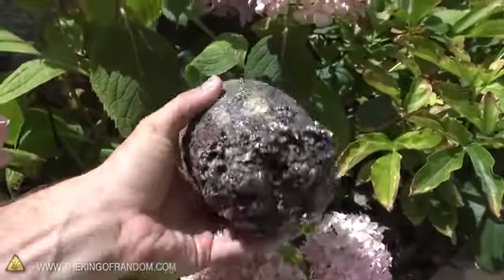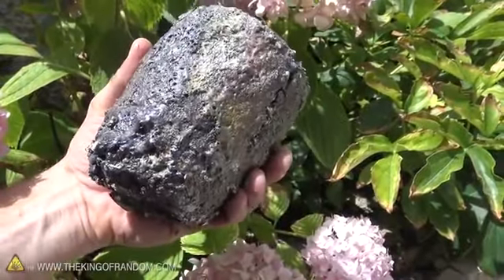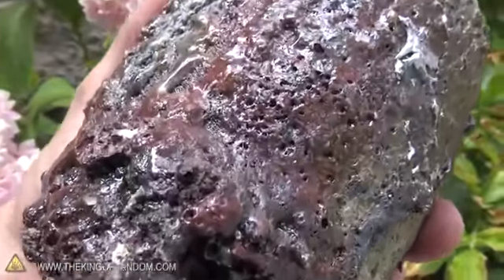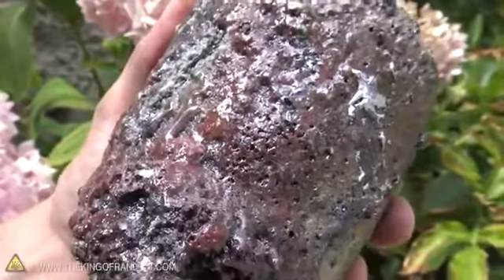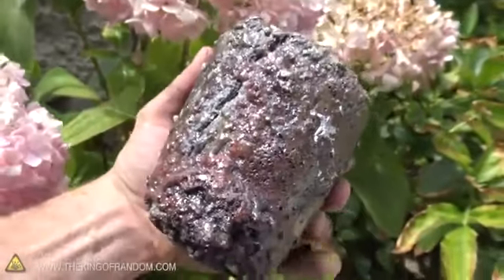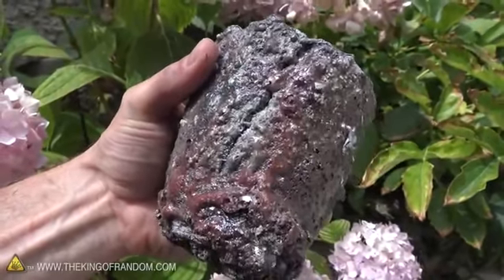I've personally put mine through over 30 different firings, and it has taken a lot of abuse. You can see it's vitrified and almost turned to glass on the edges, but I put this thing through thermal shock. I heat it up, I cool it down, I heat it up, I cool it down, I heat it up and cool it down again, and it just keeps going and going. I even cracked the side of it once, but it seemed to just heal itself.